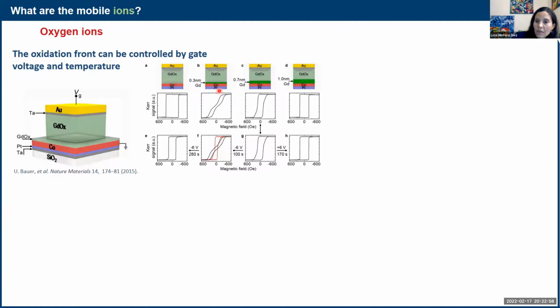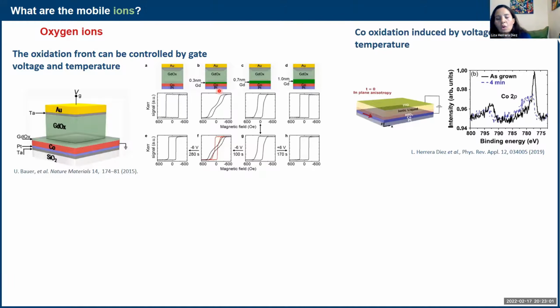So from our side, we looked at the oxidation of cobalt in platinum cobalt films with hafnium oxide, and I will go into detail later on about this. But here we could see by X-ray photoelectron spectroscopy that the metallic cobalt would transform partially into an oxide. So it would transform into this other peak that you see at higher binding energies that corresponds very well to oxidation. So this is pretty well established, that you can really oxidize your magnetic material with this transport of oxygen.